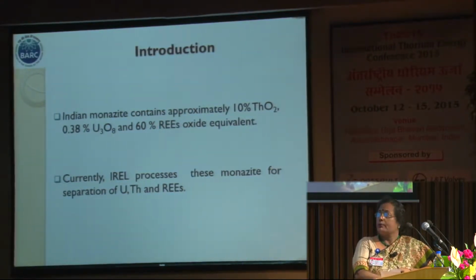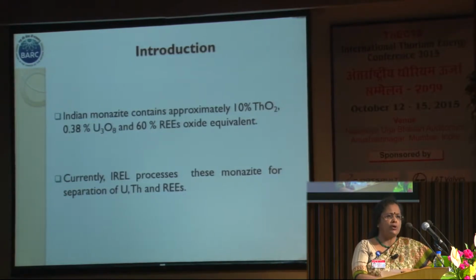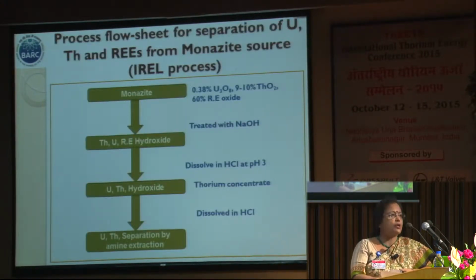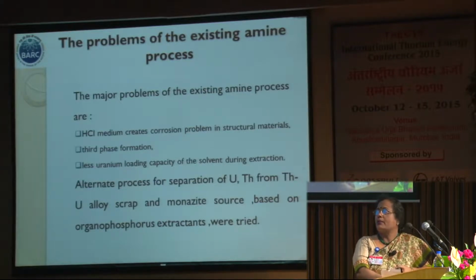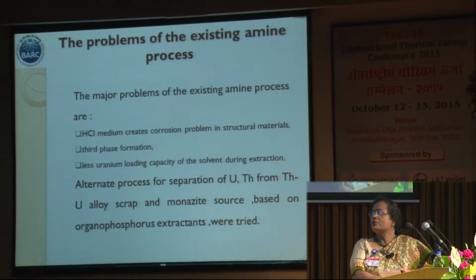Morning, Patra sahab has already said this about monazite separation. Our aim of developing this solvent extraction process was not to start this monazite activity, but whatever scrap, alloy, metals we are generating with this thorium uranium, as uranium will be in the enriched form, it was a requirement for us to develop a solvent extraction process by which we can separate the enriched uranium fully from the thorium. So on that basis we started this process, because the existing process being used at IREL, that is the amine chloride process, has problems like HCl medium creating corrosion in structural material, third phase formation, and less uranium loading capacity of the solvent during extraction.